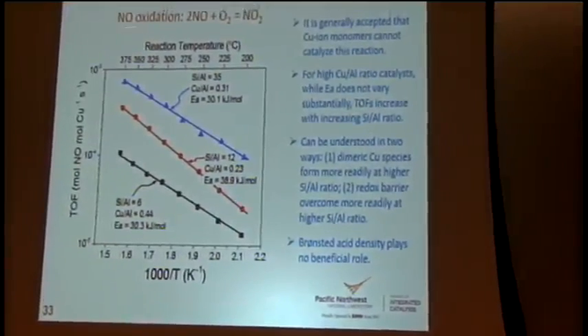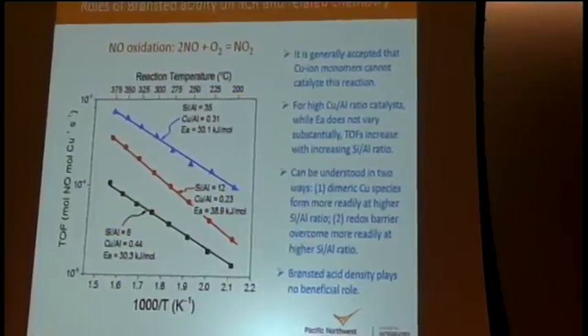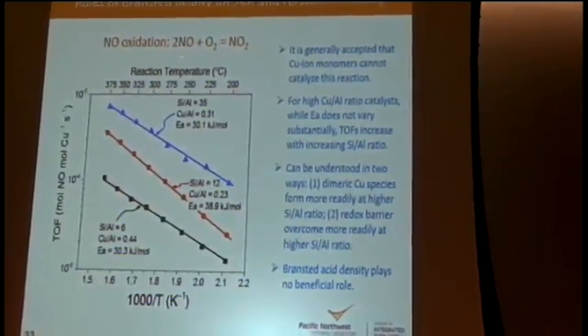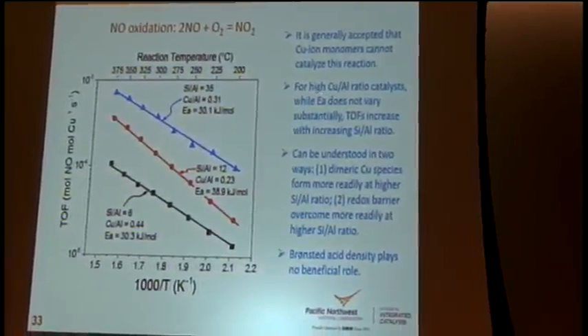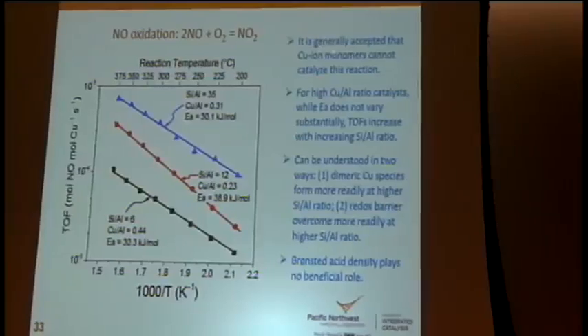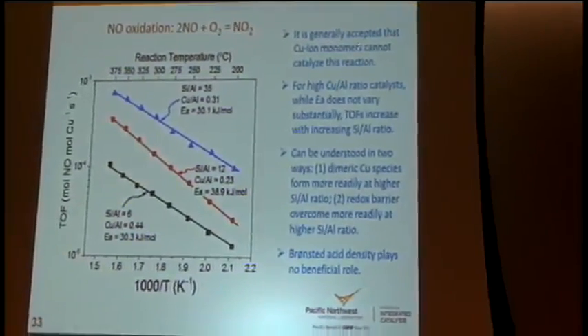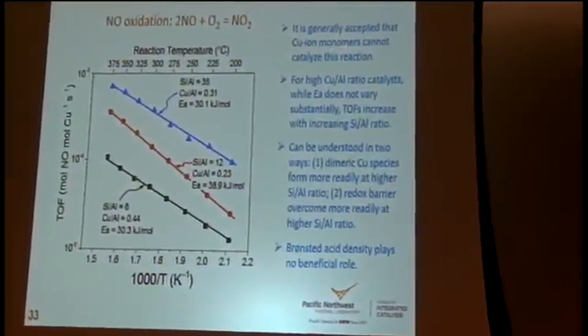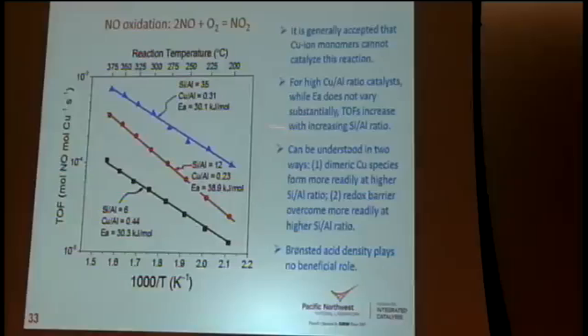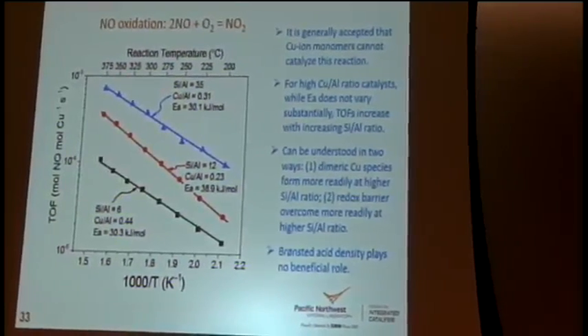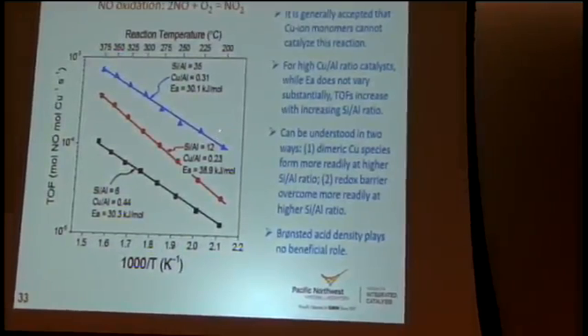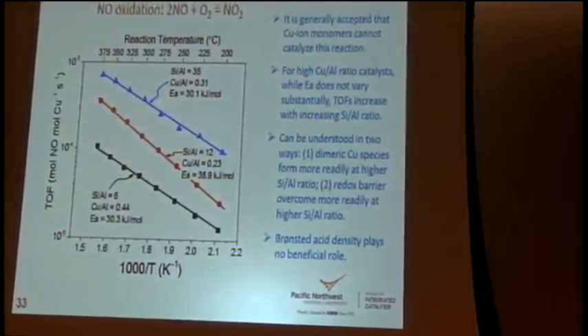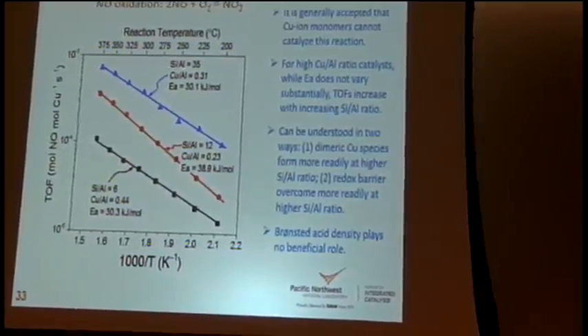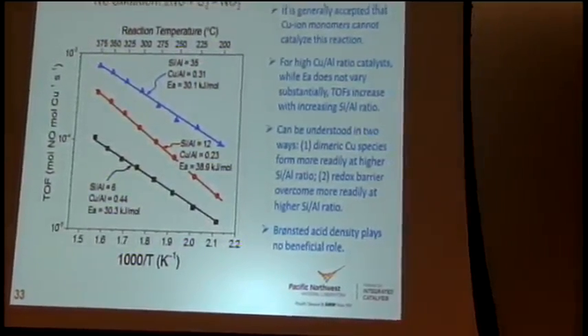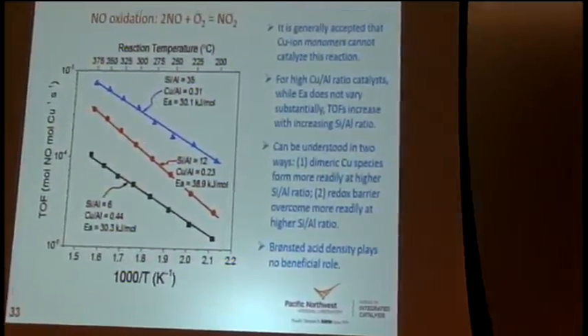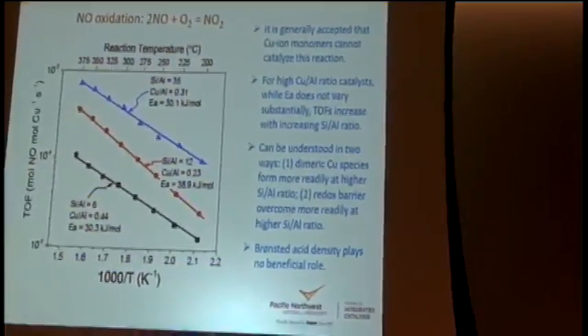Then we did NO oxidation, ammonia oxidation, and SCR reactions. This slide shows NO oxidation results. Both us and the researchers from Purdue concluded that this reaction cannot be catalyzed by copper ion monomers. So therefore, we prepared samples with relatively high copper loadings to generate dimeric species. And the interesting finding is that our catalyst with the highest silicon to aluminum ratio at 35 shows apparently higher turnover frequencies compared with the samples at low Si/Al ratios.